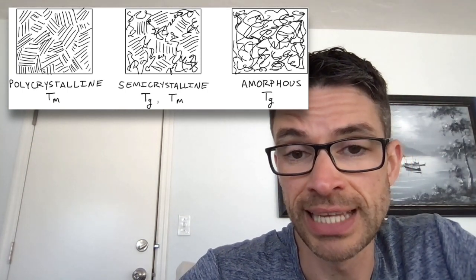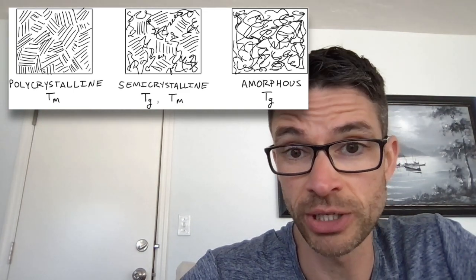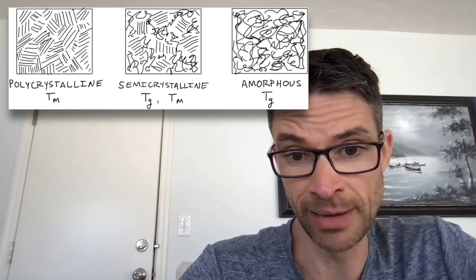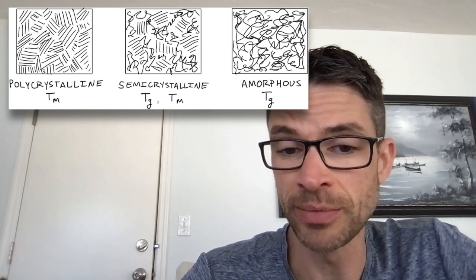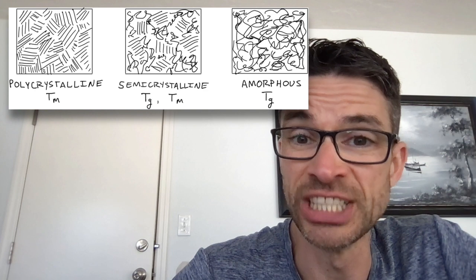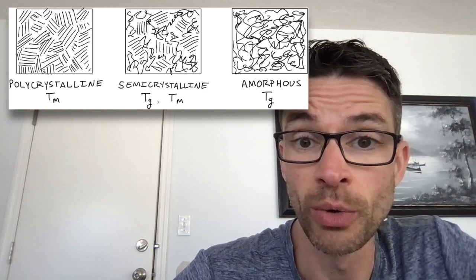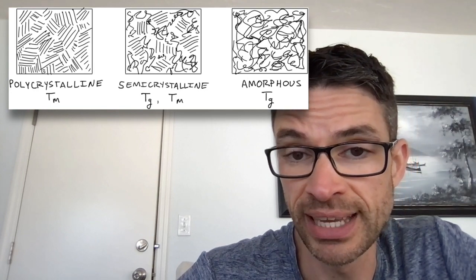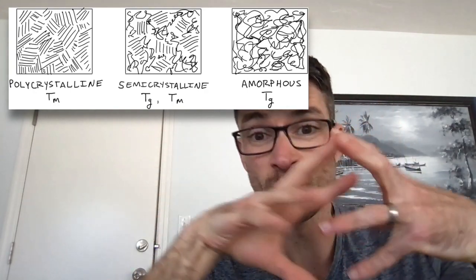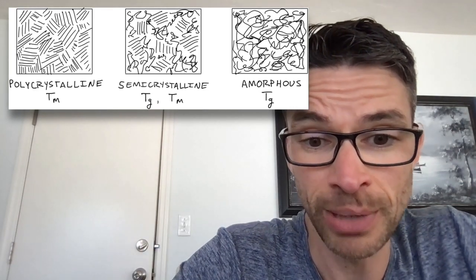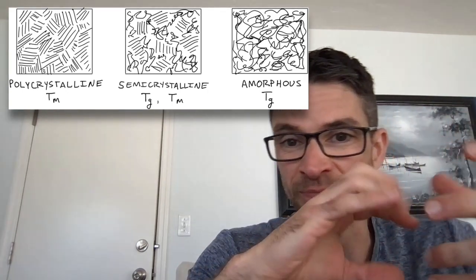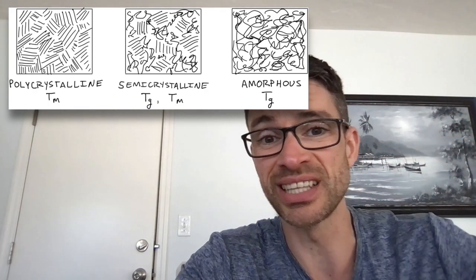A semi-crystalline sample, which is pretty common for structures with some order, has both crystalline regions — which have a TM — and amorphous regions. The amorphous regions don't have a regular repeating structure and are characterized by a transition called the TG, the glass transition temperature. Below the TG, the material is frozen, like frozen spaghetti. Suppose you cook spaghetti, it becomes loose and intertwined, and then you freeze it — that's the phase I'm describing. Above the glass transition temperature, it's like cooked spaghetti that can ooze around and the strands can slide past each other.